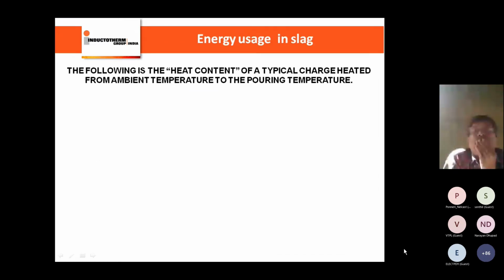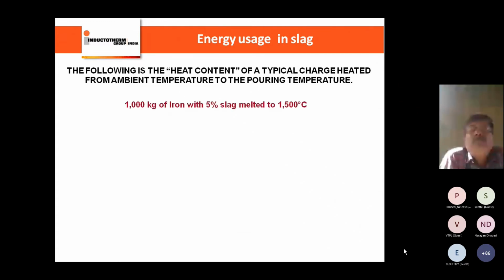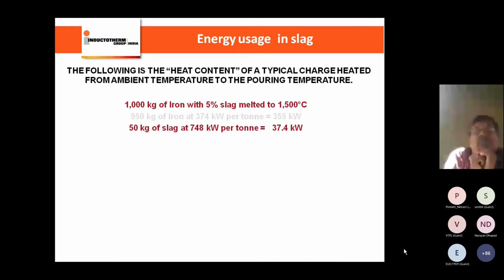So I'm going to illustrate a small energy usage in the slag formation. The following is the heat content of a typical charged heat from ambient temperature to the pouring temperature. Let's take 1000 kg of iron with 5% slag. That means 950 kg is the liquid metal out of 1000 kg being charged into the furnace, so 50 kg of slag is generated. When you melt to 1500 degrees, the 950 kg requires about 355 kilowatt plus losses, and 50 kg of slag consumes almost double the power, about 37.4 kilowatt. So the total required is 390. This is called heat content.